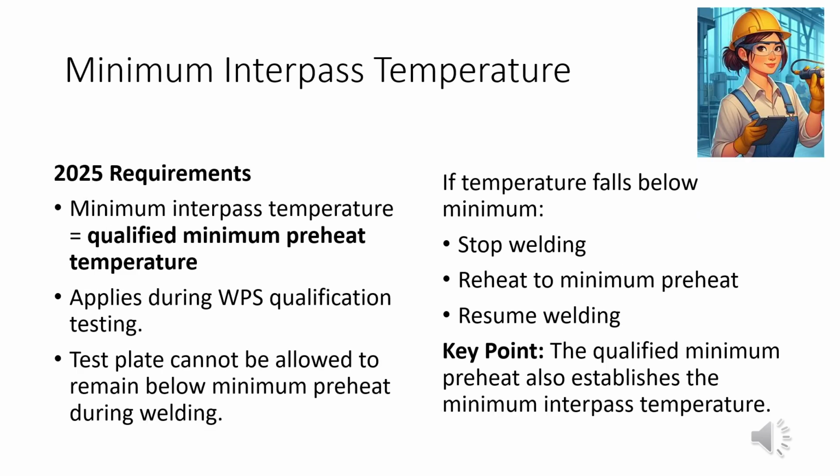Minimum interpass temperature. The 2025 edition also provides much clearer requirements for minimum interpass temperature during WPS qualification. The basic rule is pretty straightforward. The minimum interpass temperature is the same as the qualified minimum preheat temperature. During welding of the qualification test plate, we cannot allow the interpass temperature to fall below that minimum.